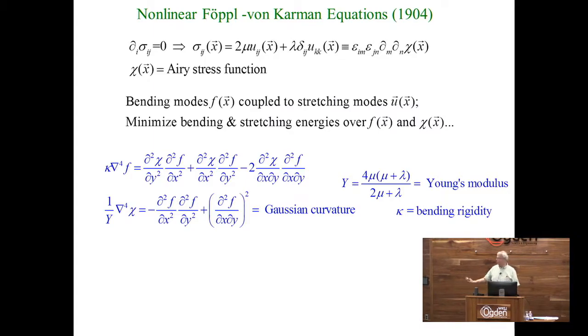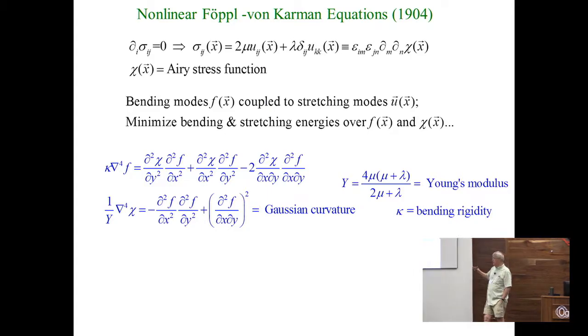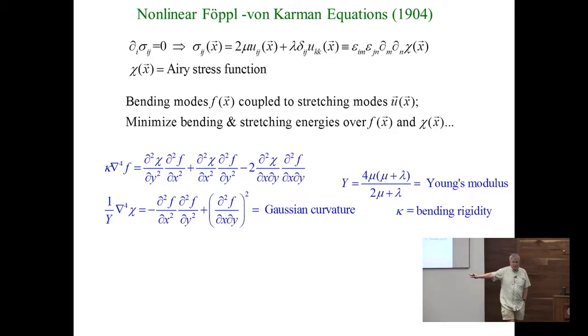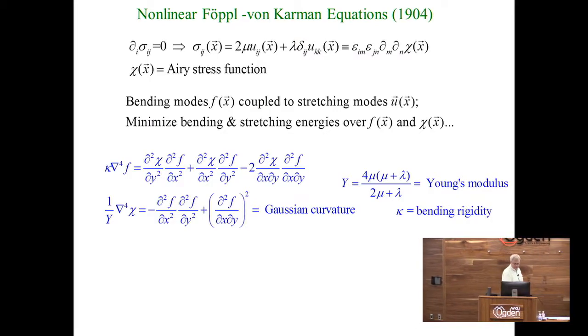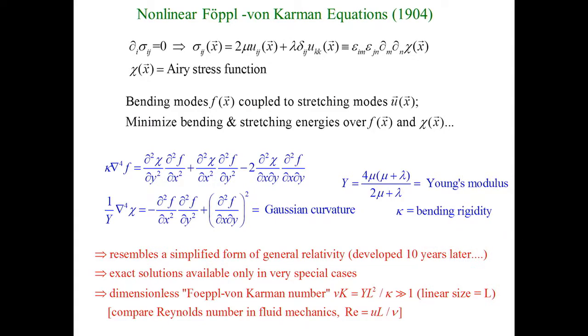And it's not exactly general relativity. It's simpler. It also has the complication that extrinsic curvature matters, as it should for these crumpled objects. But it has this nonlinear flavor. Like general relativity, the exact solutions are only available in very special cases with certain boundary conditions. And as I'll show on the next slide, there's a Föppl-von Kármán number, which I'll denote vK, like Reynolds number is Re, which is the Young's modulus times the size of the sheet of paper squared, or the size of the graphene, if you prefer, squared, divided by the bending rigidity. And the problem gets hard when this is much, much greater than 1, and that's equivalent to saying that the sheet that you're interested in is extremely thin. And as I said, for graphene, we've reached the kind of Moore's law limit of thinness.